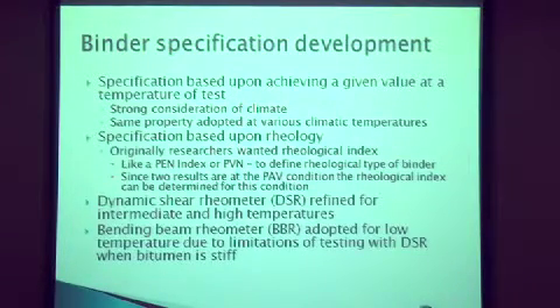The specification is based upon the rheology. The original idea in the research was to base it upon something called the rheological index. The rheological index is something like the penetration index or the penetration viscosity number. It gives some sort of indication of the temperature susceptibility of the binder. And I'll talk a little bit more about this later on. But the concept of the rheological index was felt too complicated for the average engineer. And so we made it more simple, and we used two results at the PAV condition. So by specifying two results in the PAV condition, we actually are controlling the rheological index.